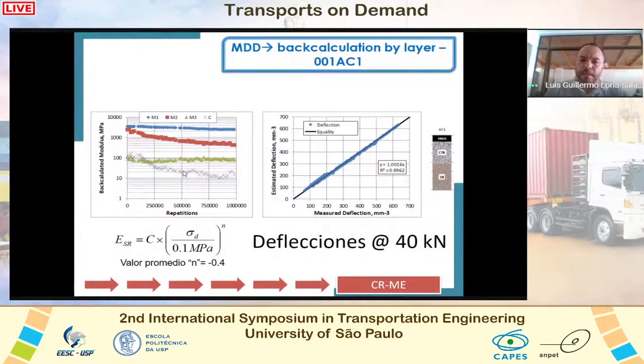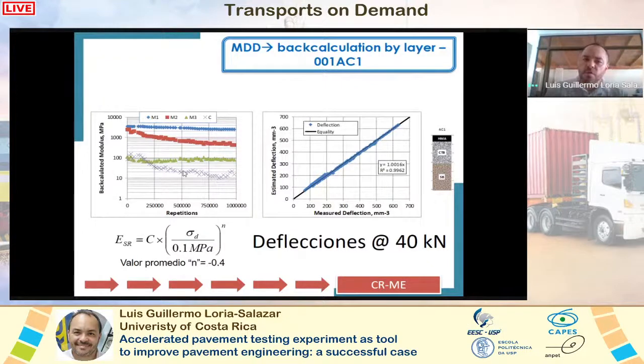Also, you can see here how you can... This is a very important thing. This is on the left-hand side. You can see a chart where you have an HMA section on top of the cement-treated base. You can see that you start doing your low repetition. The HMA has damage, but not really a lot of damage. But the red one is the cement-treated base. So you can see that the layer that is really taking care of the pavement structure, in this case, the cement-treated base, is the one that is damaged, and this result was confirmed through the whole experiment.